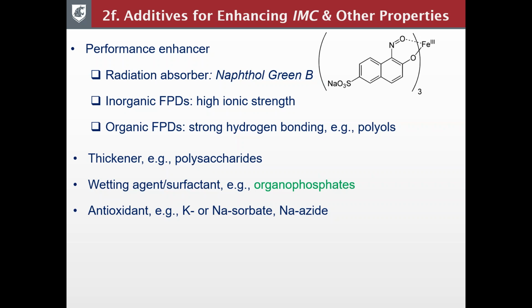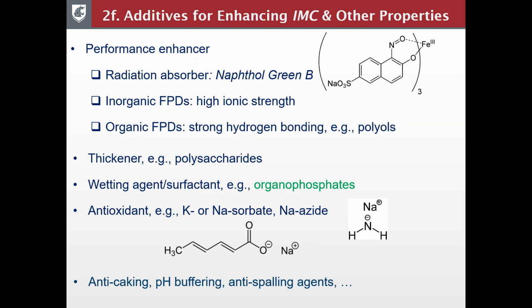And if the agro-based product is stored for a long time, we also need to add antioxidants to ensure longer storage stability. So there are also techniques available, such as the use of potassium or sodium sorbates and sodium azide. Again, there are other techniques, especially for solids, where you need anti-caking. In other cases, for instance when using metasilicate, we may also need a pH buffering agent and so on. And sometimes we use an anti-spalling agent to make sure the deicer risk to the concrete is minimized. So depending on the customer priority, different formulations could be developed.